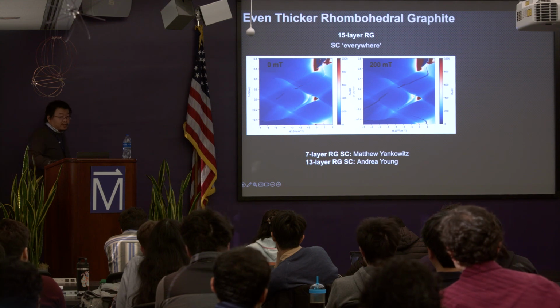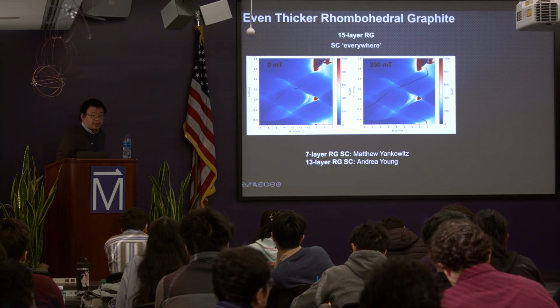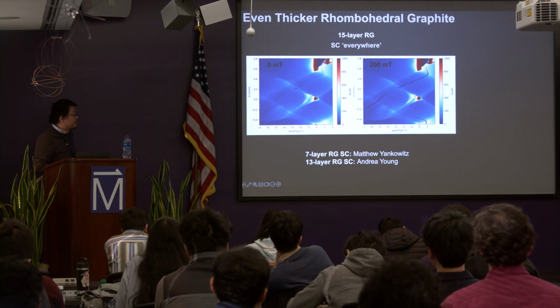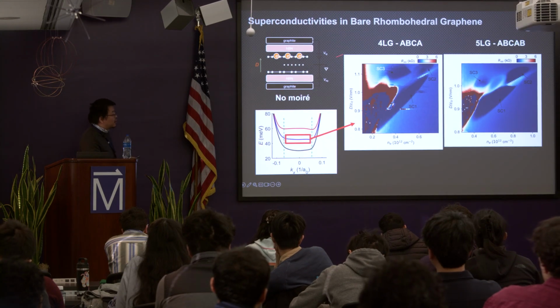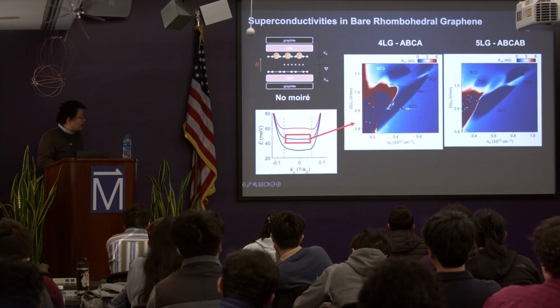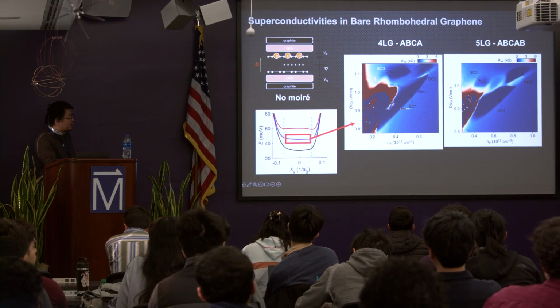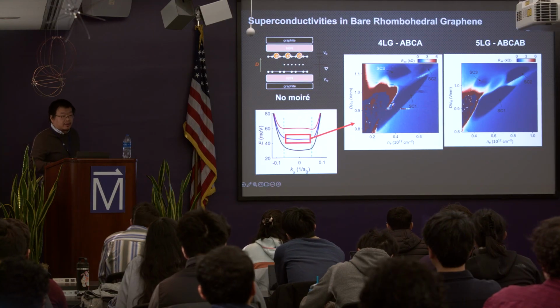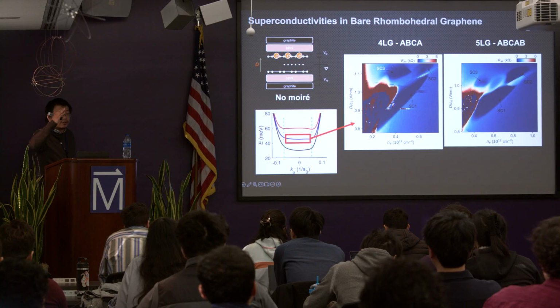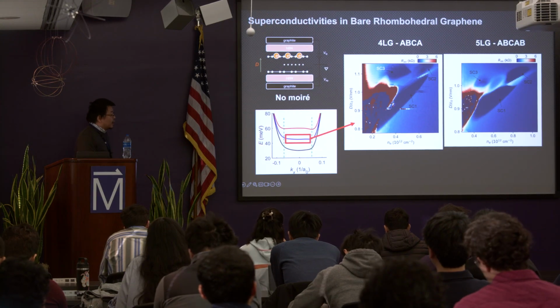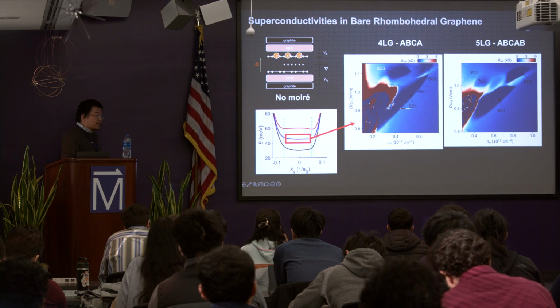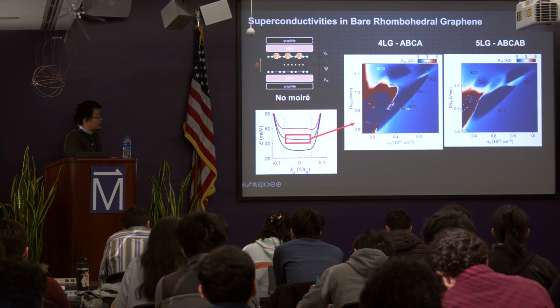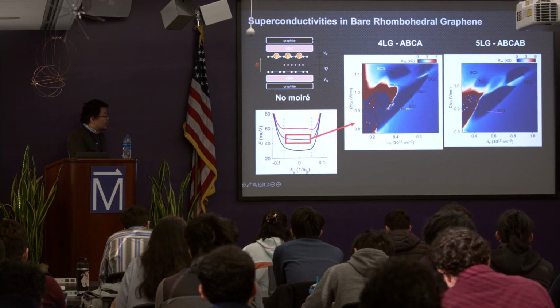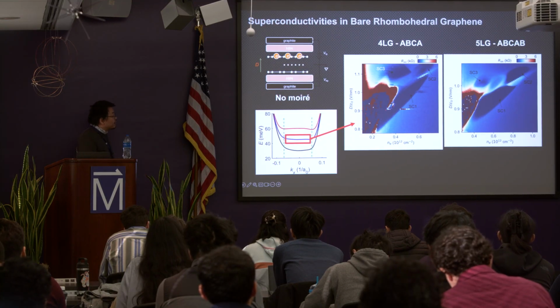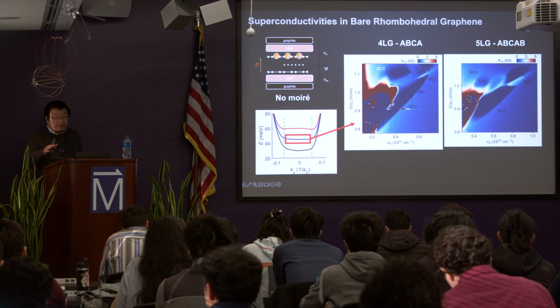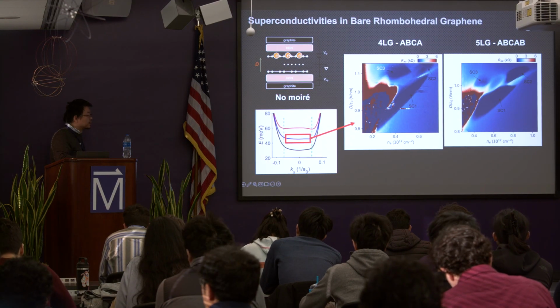So what are the differences between the superconductivity I'm talking about and all those observed superconductivity? This one is at 4, 5 or 6 layers, and it happens at a similar n-D space compared to the fractional quantum anomalous Hall effect. So you need a really high electric field that pushes the electrons to one side. And at a doping of around 0.5 times 10 to the 12th, you see these patches of superconductivity, which is the dark color. And the device itself is just pure graphite. So there's no moire, just pure graphite.